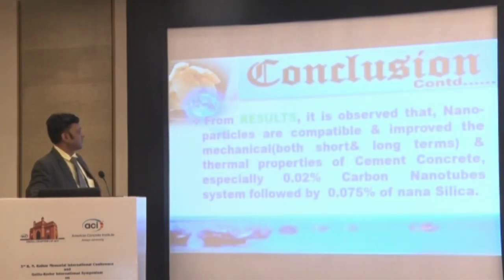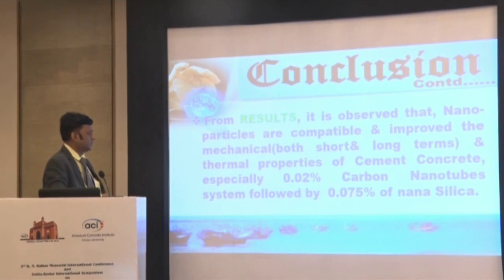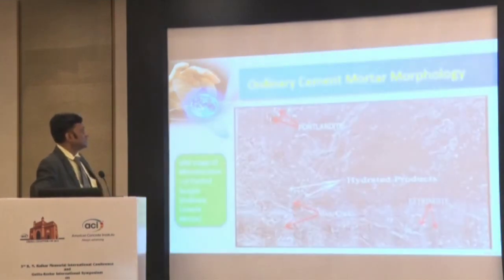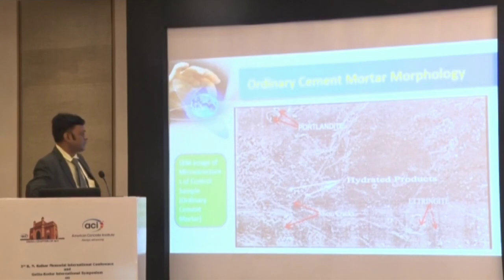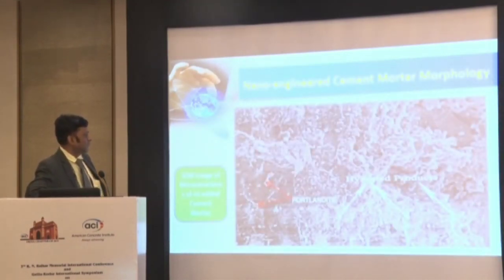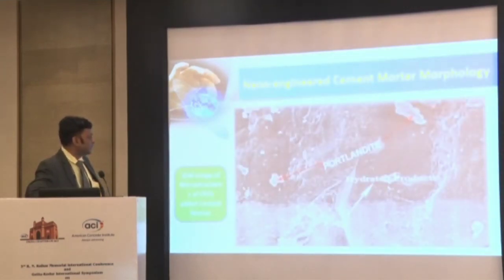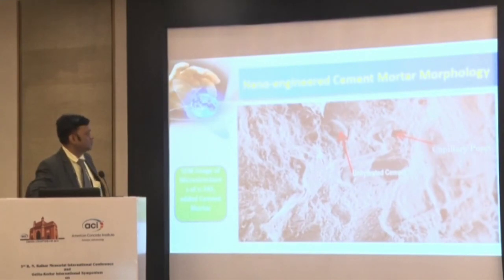From results it is observed that nanoparticles are compatible and improve mechanical properties both short and long term, and thermal properties of cement concrete, especially the 0.02% CNT system followed by 0.75%, not 0.0075, I'm sorry. These are my microstructure SEM or morphology. See the micro cracks are always there for the OPC. And with more hydrated products, micro cracks have largely vanished. For CNT, we do not get that structure, but it's more uniform. For nano TiO2, some pores have developed, and it is also uniform.